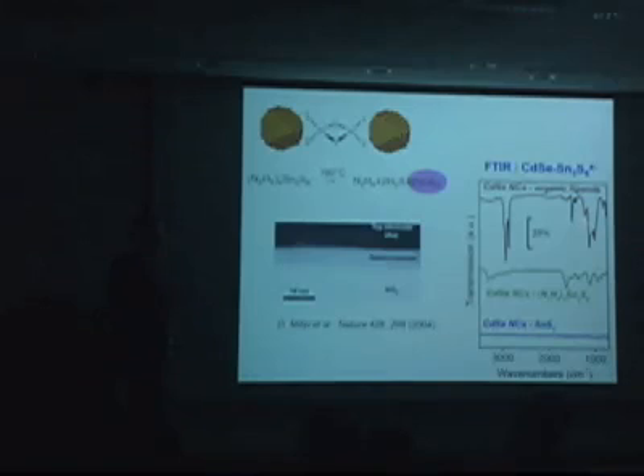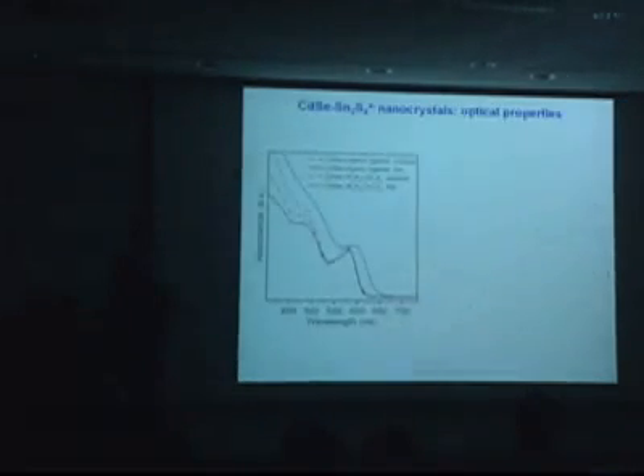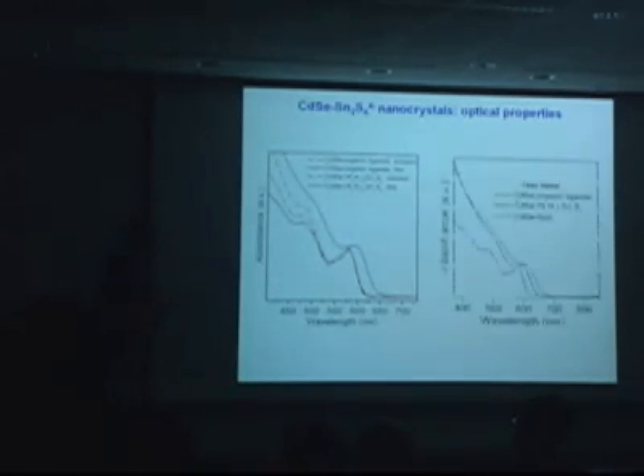To prove this, we used 3 different techniques. FTIR shows that after ligand exchange, you don't have any residual CH traces. NMR and elemental analysis also show that we for sure remove more than 99% of the original ligands. So it's quite pure chemistry, and we now have very inorganic structures where we still preserve all the benefits of quantum confinement, excitonic structure, tunability of the band gap, both in solution and in films and even after annealed films.